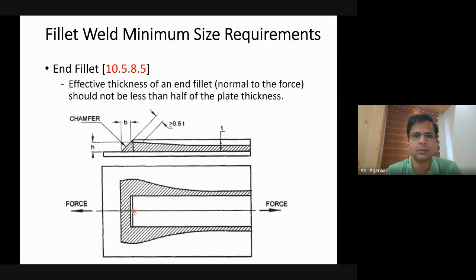So that is fine. But for the end fillet, the requirement is that the effective thickness of the weld should be at least half the thickness of this plate. So this plate is your angle leg, which is 8 mm thick. Half of it is 4, so 4 mm, and your weld size is 6 mm, and the effective thickness for that weld will be 6 divided by square root 2. So 6 divided by square root 2 is how much? 1.4, right? Approximately. So 4.2 mm. So effective thickness is 4.2 mm, and the total thickness of the angle is 8 mm. So half of that is 4 mm. So we are satisfying that requirement. Therefore, the weld size is appropriate.